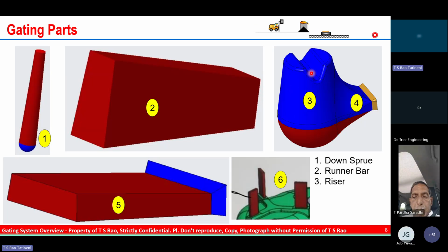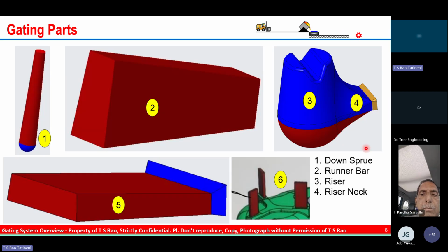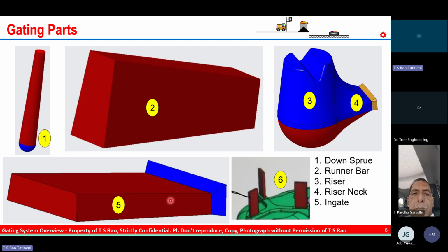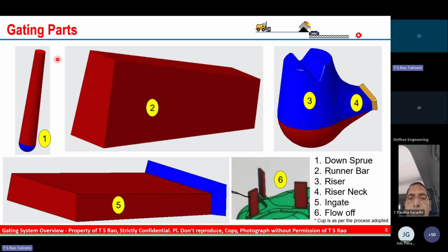For this instance, we have shown this as a sand riser because of the Williams wedge, the shape that we see here. The fourth one is a riser neck. The fifth one is the in-gate, followed by the chamfer for easy breakage. The sixth one is a flow-off and cup as per the process adopted. I have not shown the cup, but the pouring cup depends on the process we adopt. That needs to be customized, depending on the foundry process.